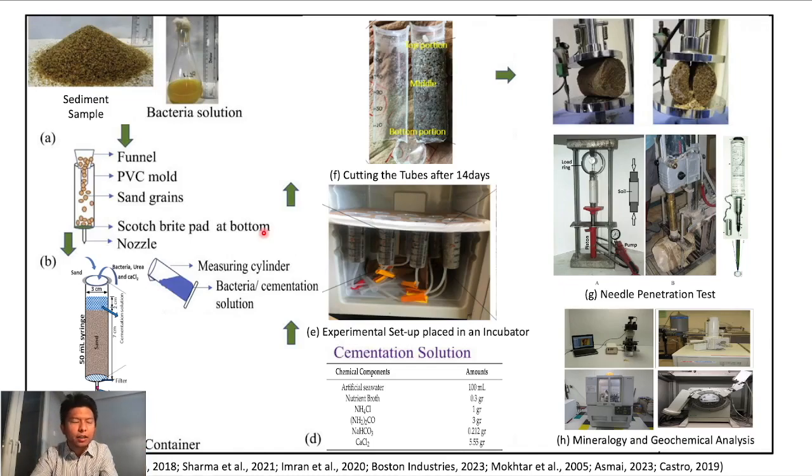Now, in the artificial Beachrock experiment, these 3 experimental setups essentially look like this, where you have your sediment sample that has the same granulometry from the site, and you mix it with the bacterial solution in this syringe setup right here. The sand is saturated with and cured with the bacterial solution, and as you can see here, we have the control valve to control the flow of the outlet solution. Again, we need to measure the pH and calcium 2+ concentration of this outlet solution, so we have the temporal gradient of these parameters because this indicates the bacterial metabolic processes that are happening.